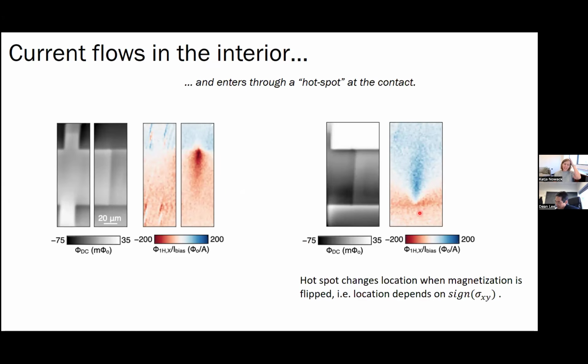And what we see instead is that the current, so here you have the outline of this Hall bar. Let's say this is the interesting topological material in lighter gray, and this is a metallic contact. Turns out when we look at the current, for some reason it comes in through a very bunched up corner of this contact up here, and then just spreads uniformly into the sample. And if we change a characteristic of the sample, we can actually flip the corner at which the current comes through.